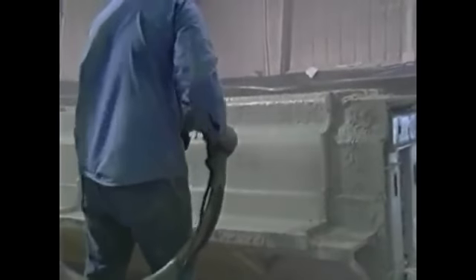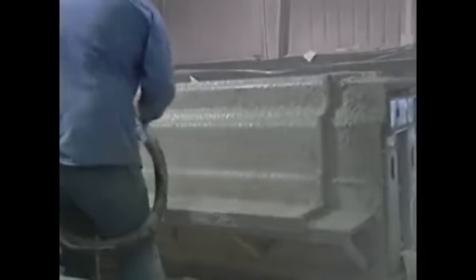Several layers of the composite are deposited and compacted until the required backup thickness, usually 1/2 to 3/4 inch, is achieved. Consolidation between layers is done with rollers, which compact the backup mix, remove entrapped air, and bond the face mix to the backup glass fiber mix. Quality control checks on thickness are made regularly during the spraying operation to ensure a uniform thickness of the finished